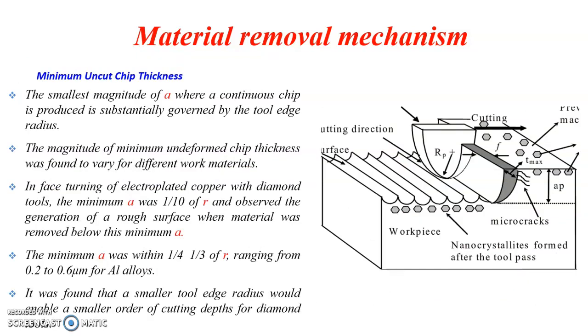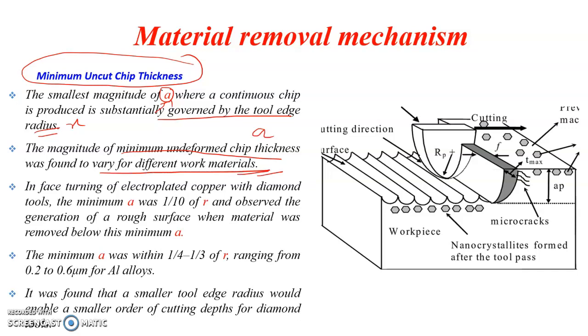The next term is the minimum uncut chip thickness. The uncut chip thickness is given as small a. There will be a minimum for this uncut chip thickness. The value of A is governed by the tool edge radius R, and the magnitude of the minimum undeformed chip thickness A was found to vary for different work materials. As an example, in face turning of electroplated copper, the minimum A is recorded as 1/10th of R, and a rough surface was observed when material was removed below this minimum A.